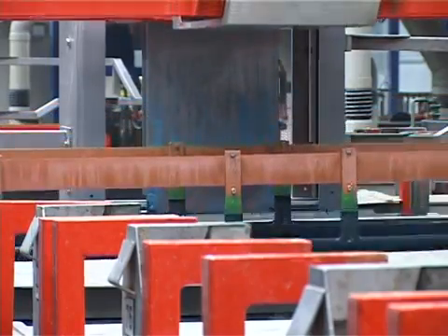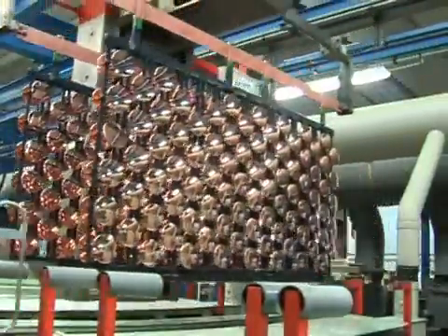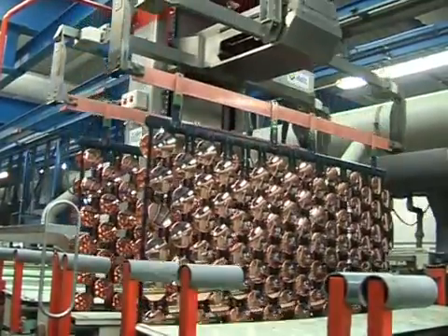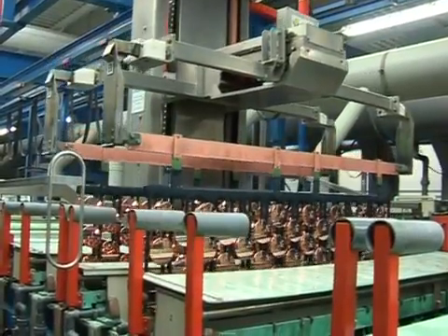Next, a 20-micron thickness layer of copper deposited from an acid copper electrolyte provides leveling of the etched plastic surface, while also producing a bright, smooth deposit. This layer also provides ductility between the plastic and other plated layers, which is important to improve the thermal shock resistance, while also minimizing the formation of cracks when the plated part is in service.